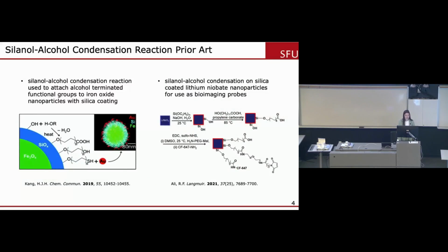This has been performed in our group in the past, and it is a great advantage over using silane reagents, which are more commonly used. Silanes suffer from the moisture sensitivity that they have, and they must be worked up in a glove box oftentimes. And they're really difficult to manage and reproduce the results of. They can create islands on nanoparticle surfaces, which are non-uniform, and that makes the additional steps after the functionalization much harder.